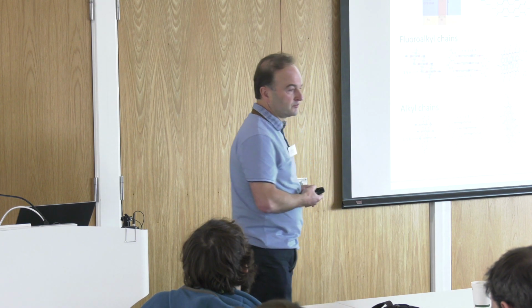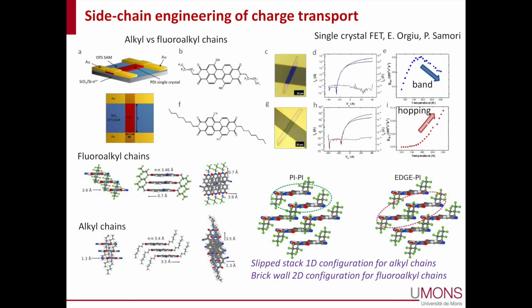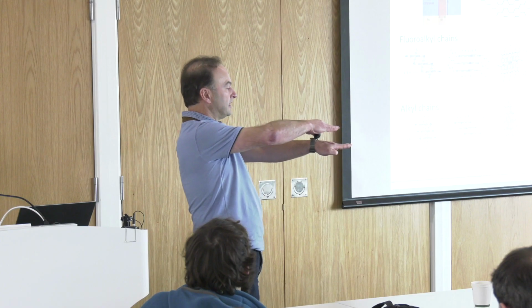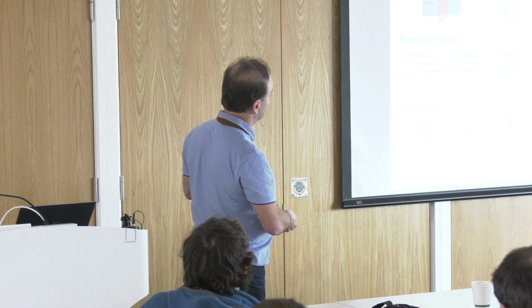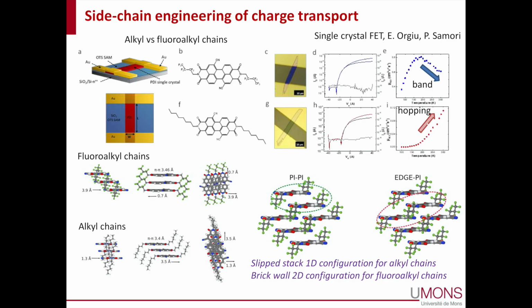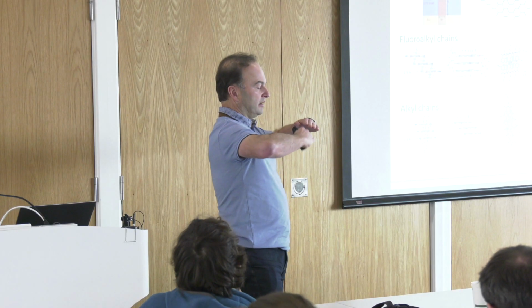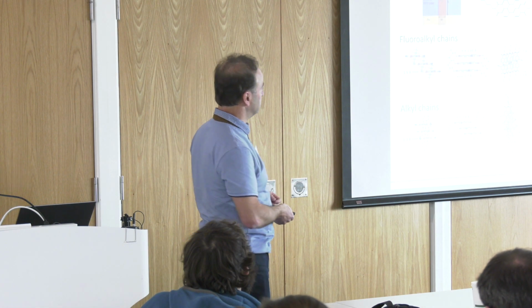And so the first thing to realize is that the stacking structure of the two molecules is slightly different. It's more of a one-dimensional slip stack configuration in the alkyl case. So the molecules are slip stacked. They are not exactly stacked on top of one another, but slightly shifted. But essentially it's a 1D arrangement. While for the fluorinated side chains, there is also a little bit of edge-pi interaction. So the system is more like a brick wall configuration where the transport can be two-dimensional. So you have quantum mechanical interaction in 2D versus 1D. So that's already one big difference.